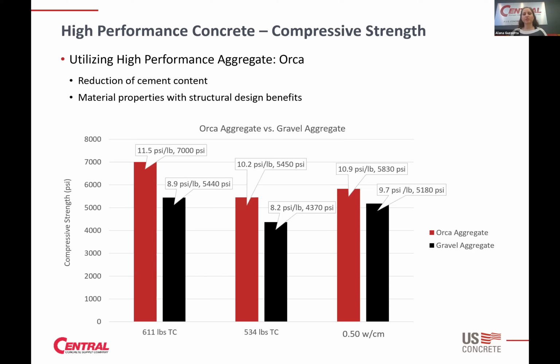And so for the example that you see here are 3 different types of mixes. And we've got one example with our Orca aggregate for each one of those, which are the red bars. And then the black bars are a local kind of standard quality gravel. And what you can see is that we're measuring cementitious efficiency in terms of PSI per pound. And so we're above 10 PSI per pound by using the Orca aggregate. And we're within the 8 to 9 PSI per pound range, but with a different aggregate. And so with that, the Orca mixes are going to require less cement to achieve the same compressive strength.